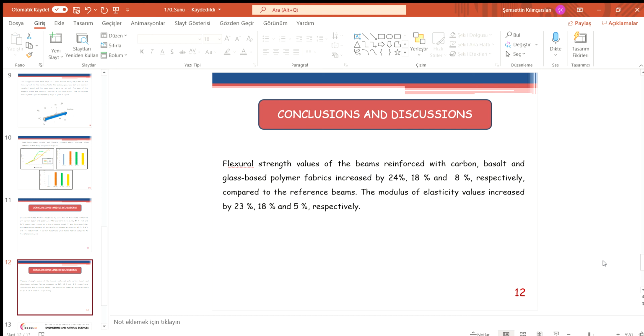Flexural strength values of the beams reinforced with carbon, basalt, and glass-based polymer fabrics increased by 24%, 18%, and 8% respectively compared to the reference beams. The modulus of elasticity values increased by 23%, 18%, and 5% respectively.